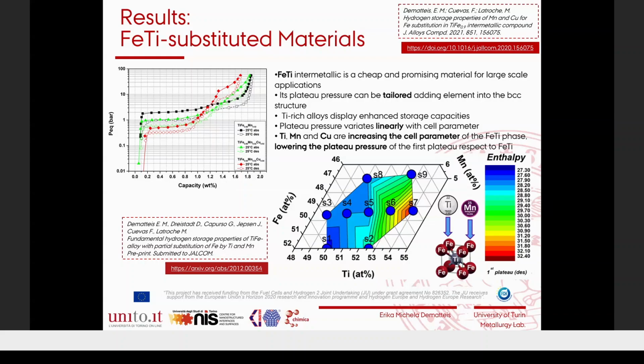and milder condition. And the first graph is reported and the study has been recently published, while in the second scheme, we can observe that by elemental mapping in the titanium, iron, and manganese ternary system, we can play with the composition that lead us to also determine a variable thermodynamics of the system. So the enthalpy of hydrogen release can vary with the composition and of course with the alloying, the elements we are introducing.